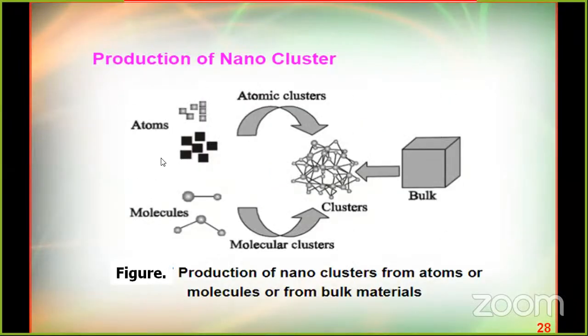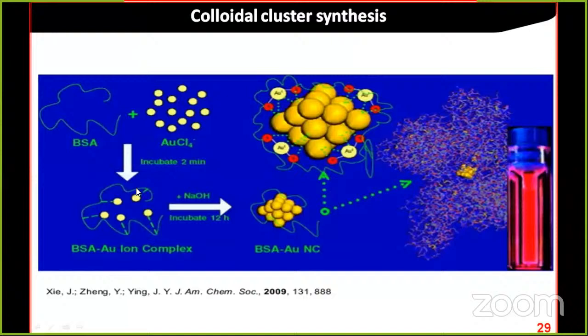The synthesis, as I mentioned earlier, is the bottom up approach. This is the top down method. So you can prepare it both ways. There are many things. This is the best paper, by Xie et al., published in 2009, using bovine serum albumin as a capping agent. This protein is simply mixed with gold chloride and bovine serum albumin, incubated 2 minutes, and after that sodium hydroxide is added. They incubated and stirred for 12 hours at 38 degrees in dark room condition. The next day they got the red fluorescence.